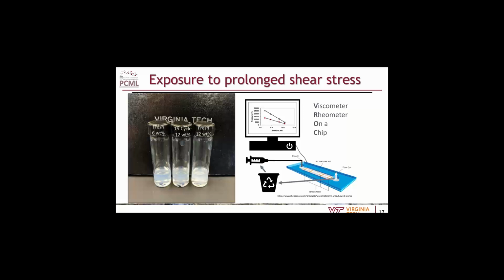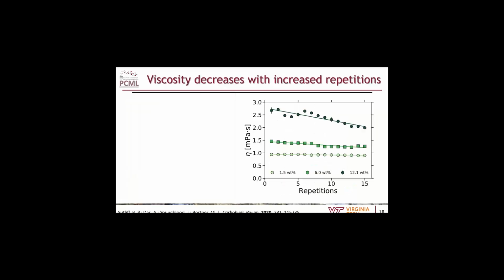I took a couple of different concentrations and just ran them through the syringe a couple of times. What happened was, with each repetition, my viscosity decreased. What I would have expected was my concentration to slowly go up as I lose moisture from evaporation, etc. But instead, this happened. As we increase concentration, we see a much more dramatic decline in our viscosity over time.